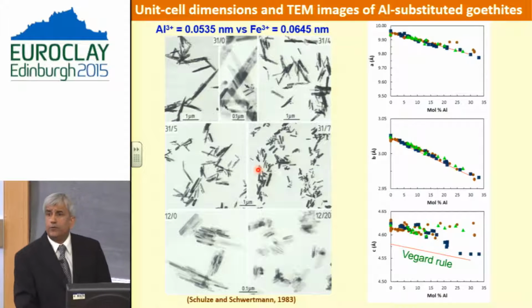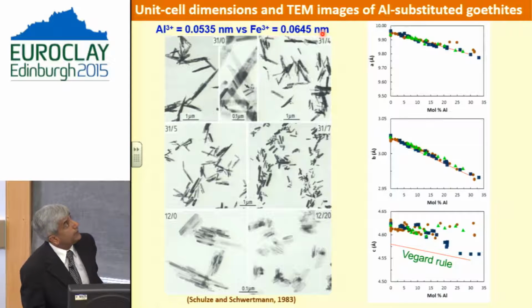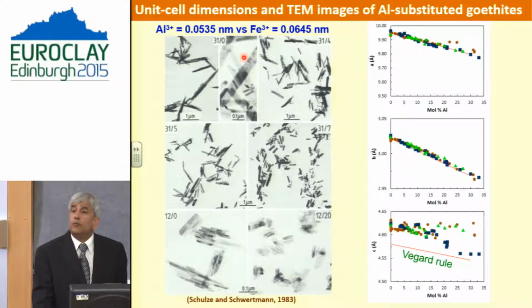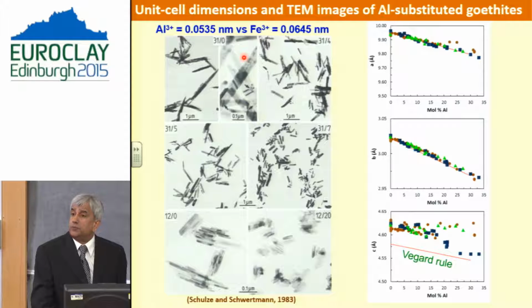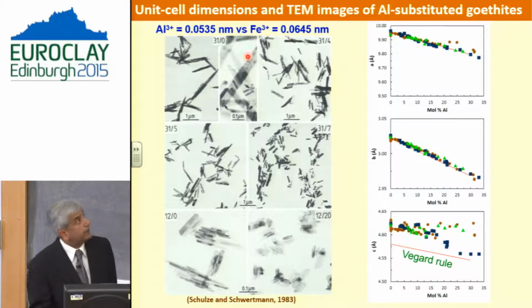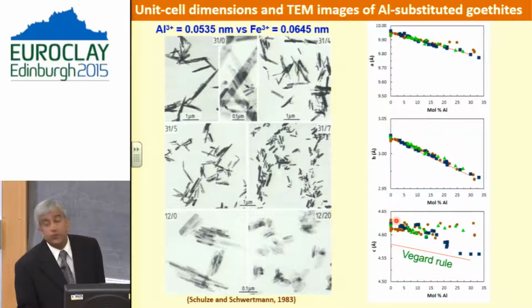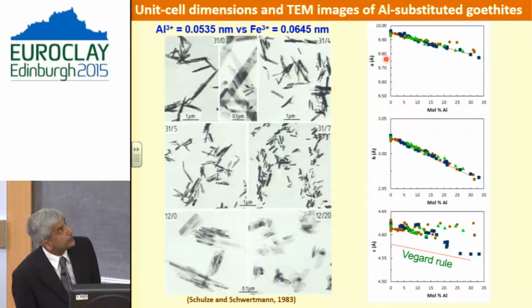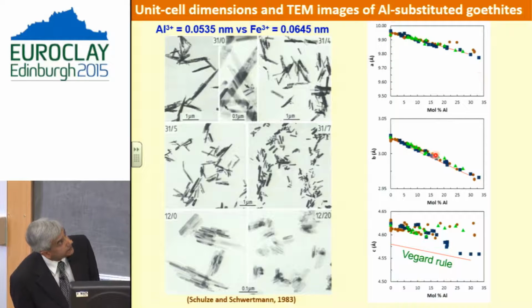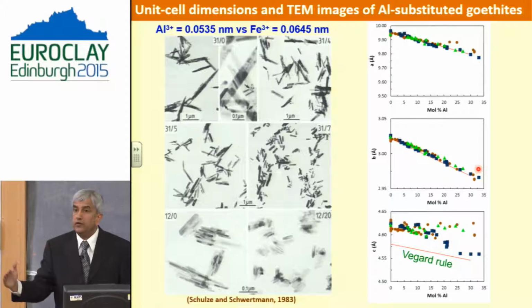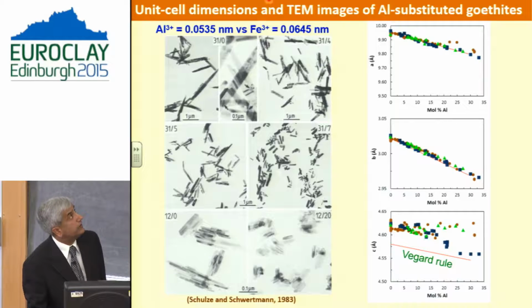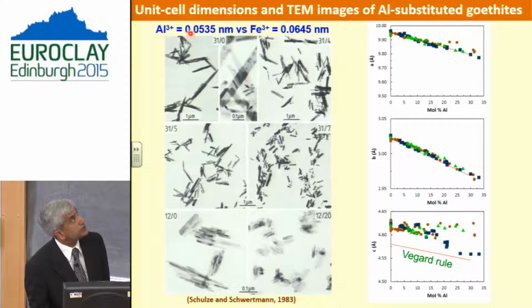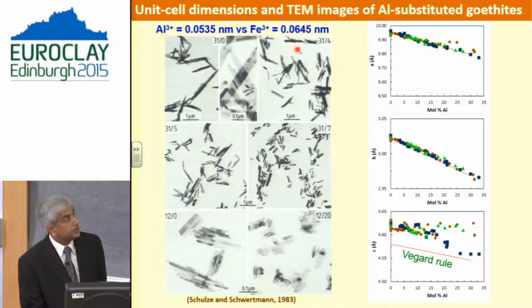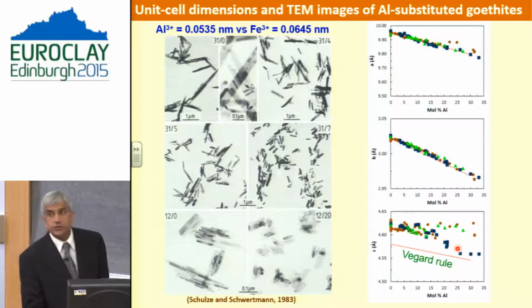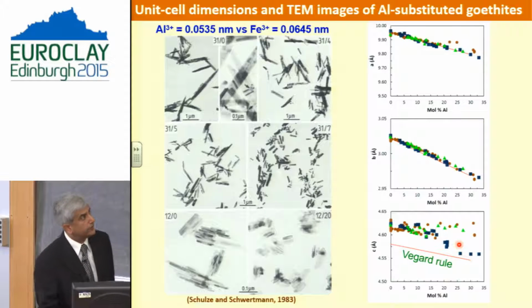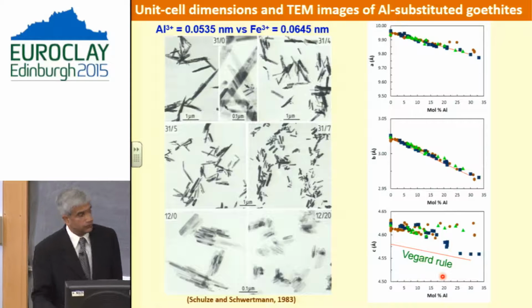The first one obviously was demonstrated for aluminium, and almost 1/3 of the iron 3 can be substituted by aluminium, and that obviously has an effect on the unit cell parameters of the mineral. Here you can see the cell parameters a and b almost linearly decreasing as a result of substitution. And as you can see, the size of aluminium is obviously much smaller compared to iron 3. The same trend was not evident for dimension c, where it's not following what we call the Vegard rule.